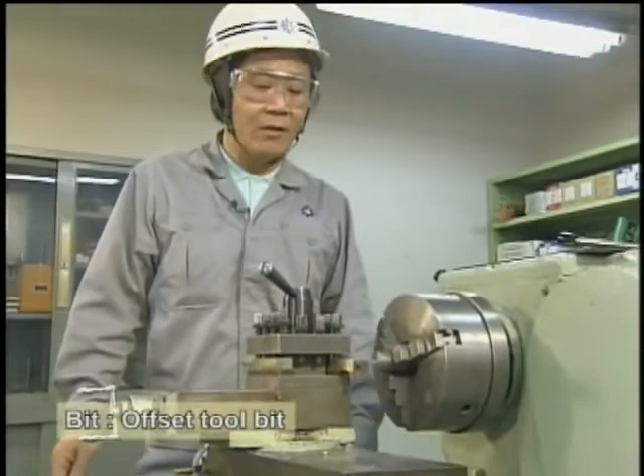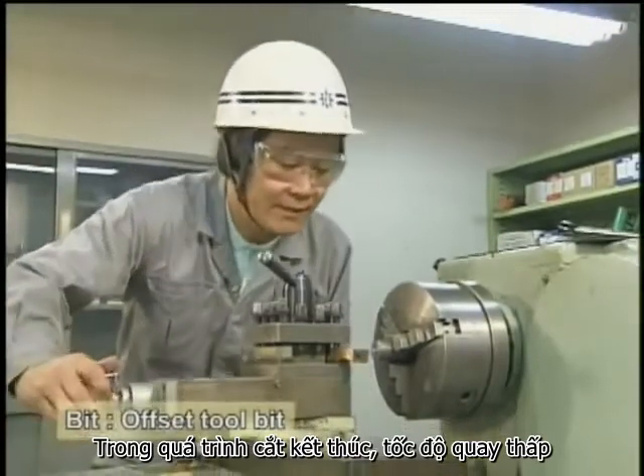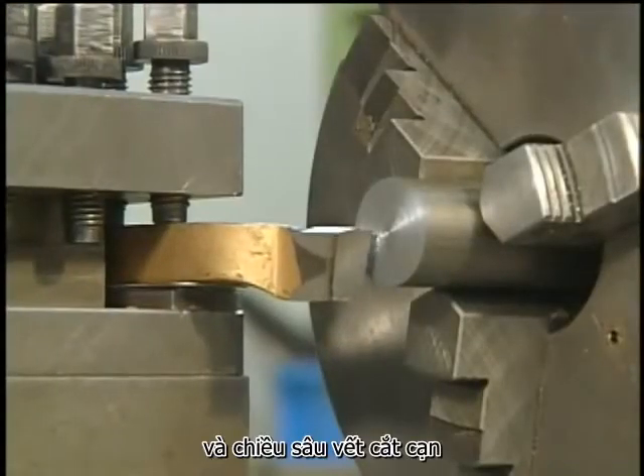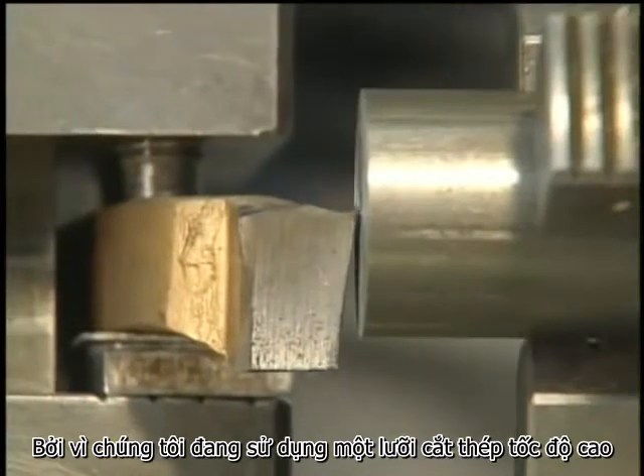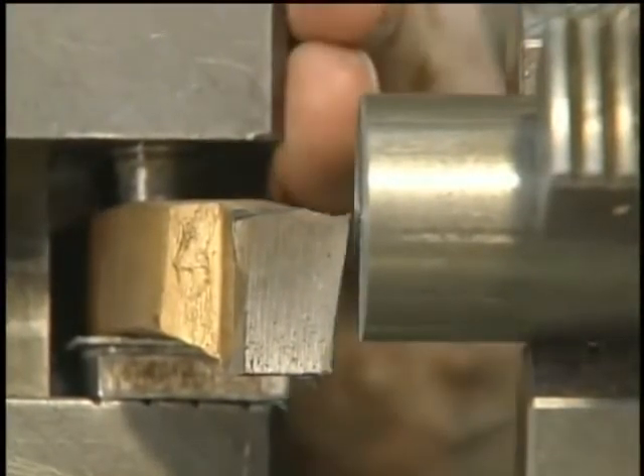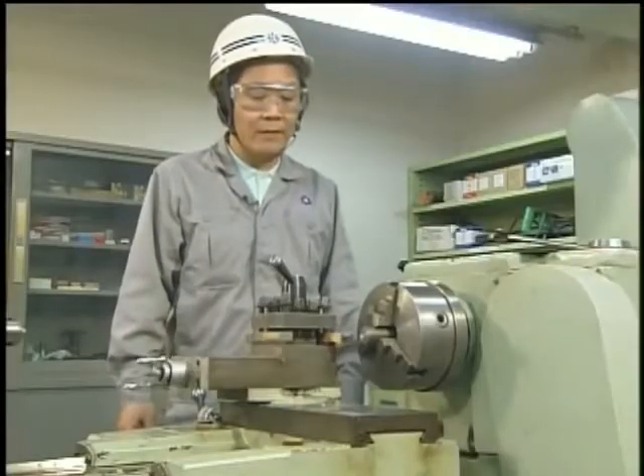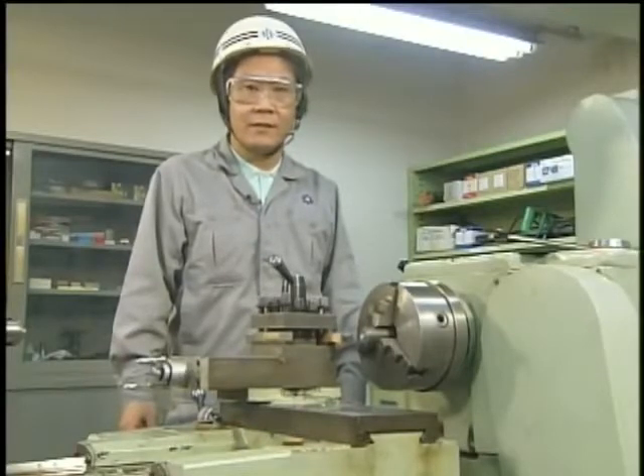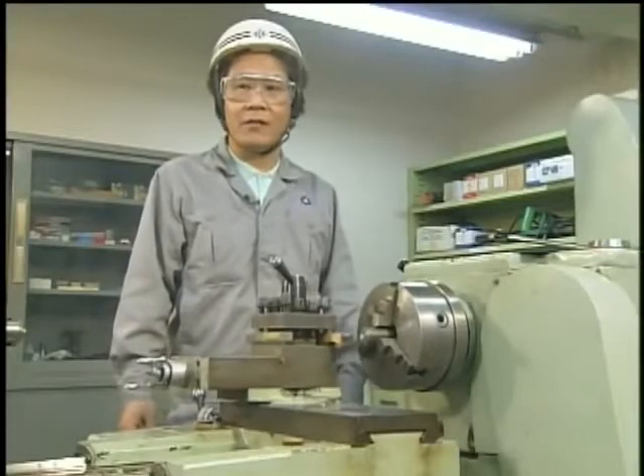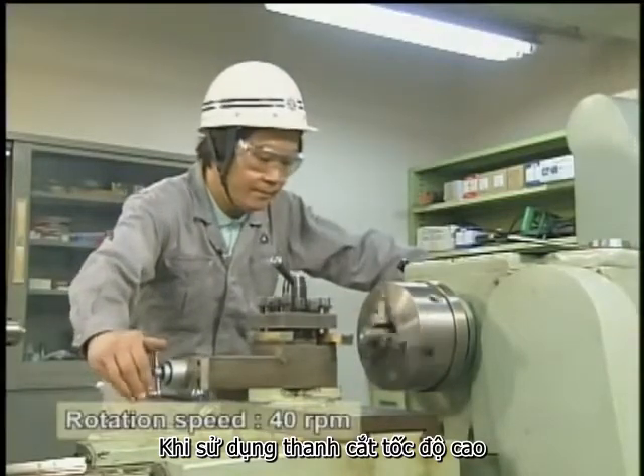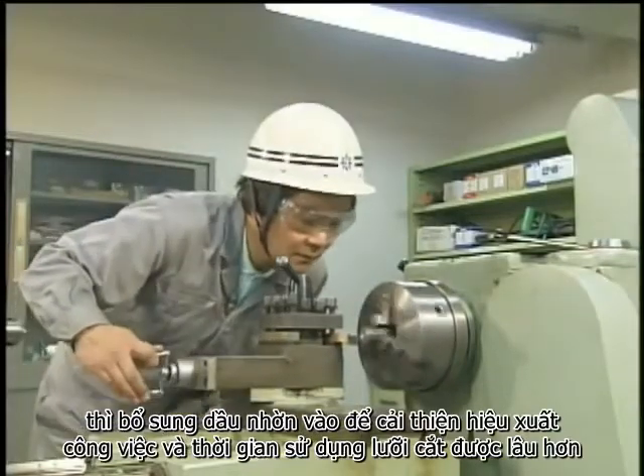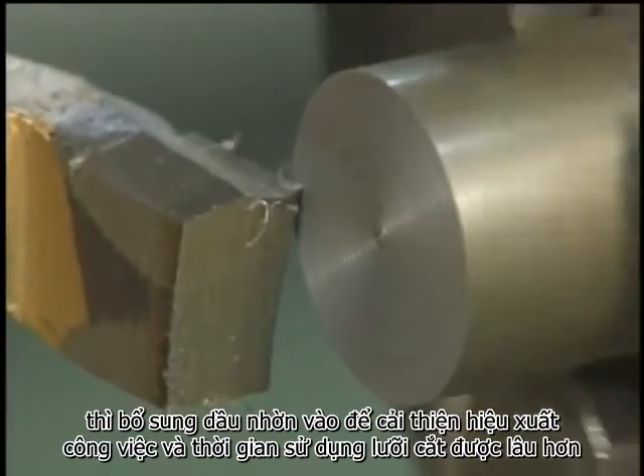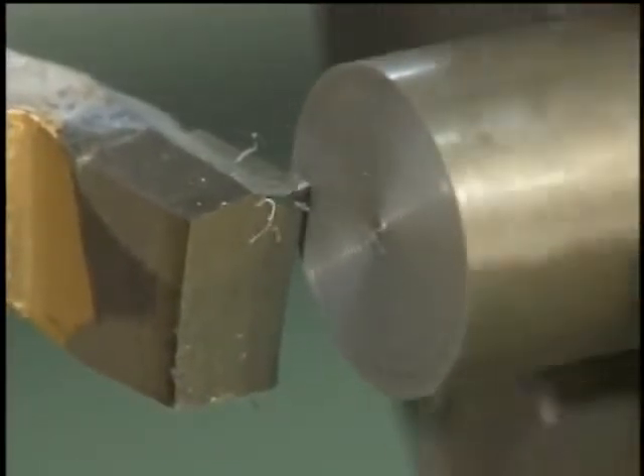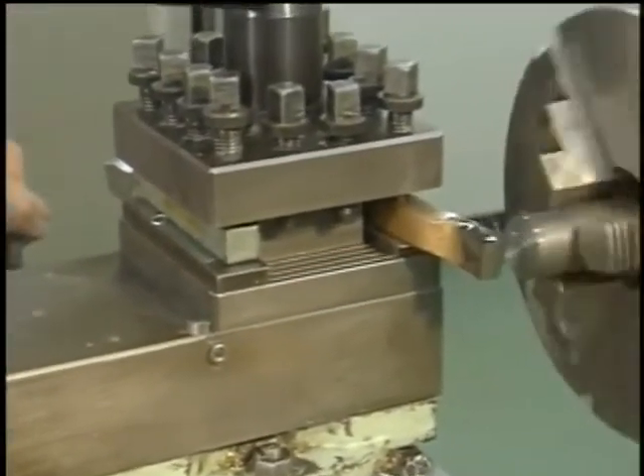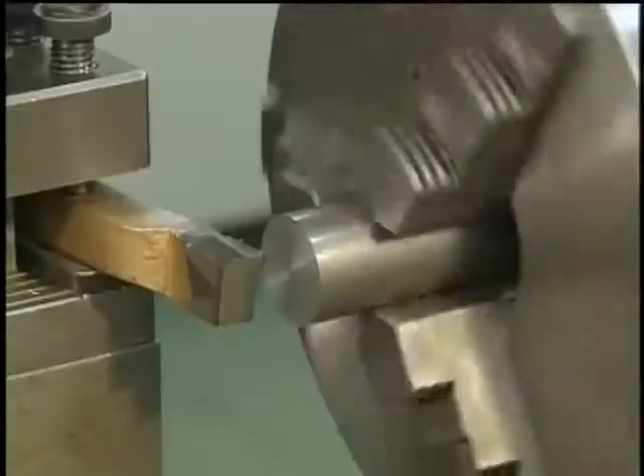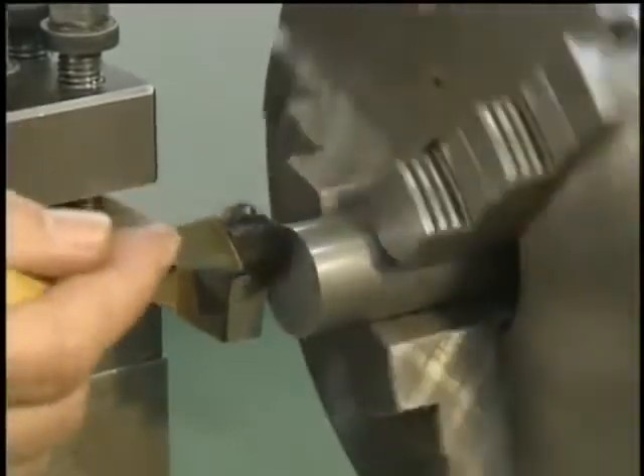Now it's time to finish the ends. The bit used is an offset tool bit. Adjust the bit so it touches the workpiece horizontally. In the finishing cutting, the rotation speed is low and the depth of the cut is shallow. Because we're using a high-speed steel finishing bit, the rotation speed is only 40 RPMs. When using a high-speed steel bit, apply lube oil to improve the finish and the working life of the bit.